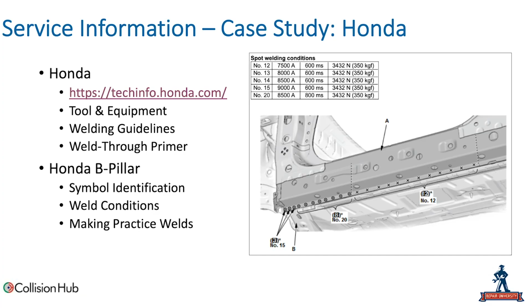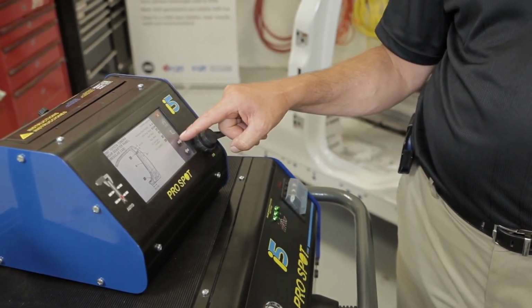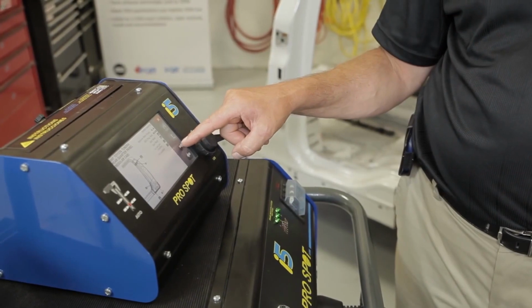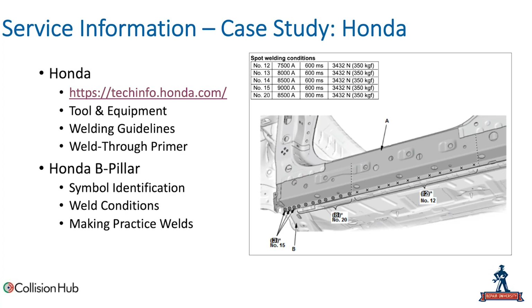So if I go back, I pulled up the Honda B-pillar replacement procedure, or the rocker panel replacement procedure, and you can see on here they have 5 different welding conditions for this particular part. In the front of the rocker panel, towards the A pillar, weld condition number 15 requires 9,000 amps for 600 milliseconds. The next 8 welds, weld condition number 20, 8,500 amps. And then the next several welds, weld condition number 12, 7,500 amps. So we need to make sure that we're adjusting that machine for each of those different welds. Again, we're going to make our first 3 welds at 9,000 amps, then our next ones at 8,500 amps, and then the next ones at 7,500 amps.